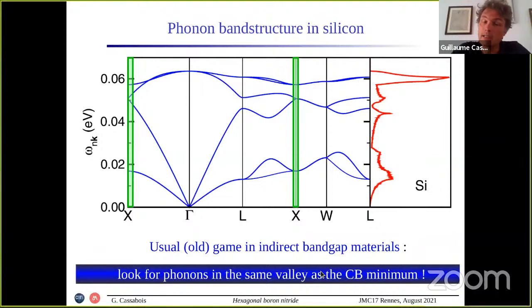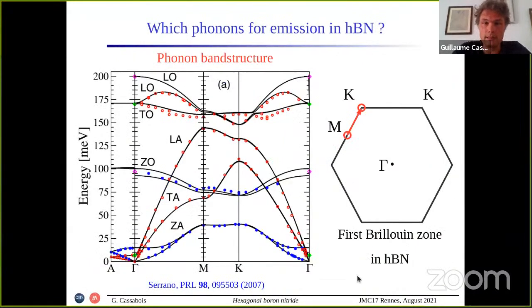And in HBN, it's not the case. Let's go back to the first Brillouin zone of HBN. On the left, I'm plotting again the phonon band structure, from a different reference than before. So I told you that the valence band maximum was around the K point, and the minimum of the conduction band was at the M point.